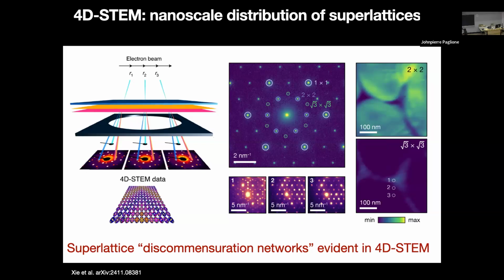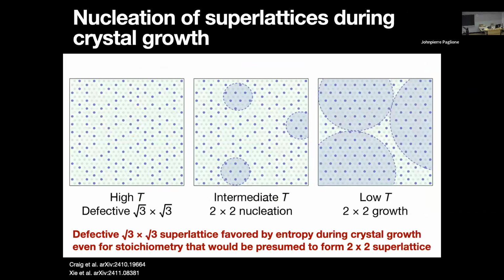And when we do the 4D STEM experiment and scan to figure out where in space these are, we see these regions: the green domains are the 2x2, and the dark regions are where there is no 2x2. If you then use the electron beam from the √3×√3 reflection to form the image, that's where you see it, right? This is precisely what we were expecting to see.